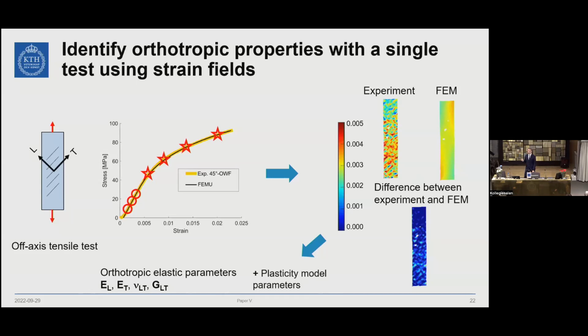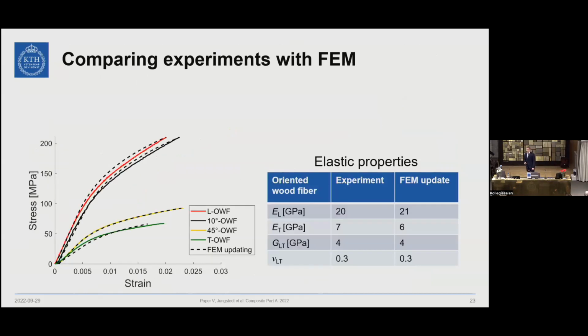And then we can see that the finite element model actually predicts very well with the experiments. And of course, we need to validate this. So we did other tests in different directions, and we can see how well it actually performed. So we are quite close to the experimental values.